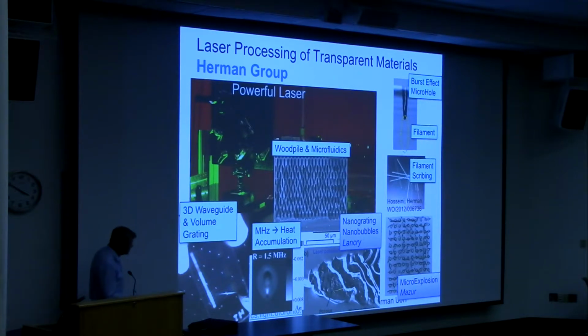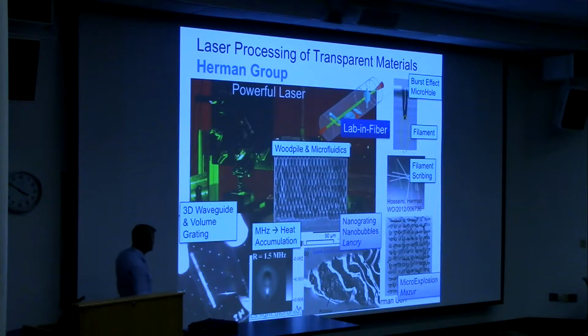Rod Taylor at NRC Canada just added acid to these glass structures and found the acid would etch quickly along these grating planes controlled by polarization. So we took that effect and showed that you can make this microstructure, I'll come back and say more about it, with really high resolution. It's an inverted woodpile structure. So what you see here is refractive index changes that are patterned into waveguides or gratings, or 3D structures, which is a neat processing technology of very high resolution.